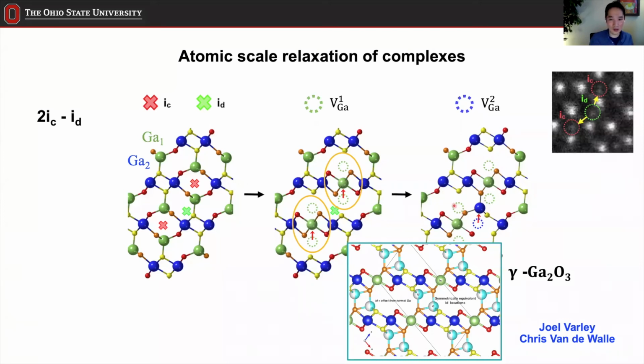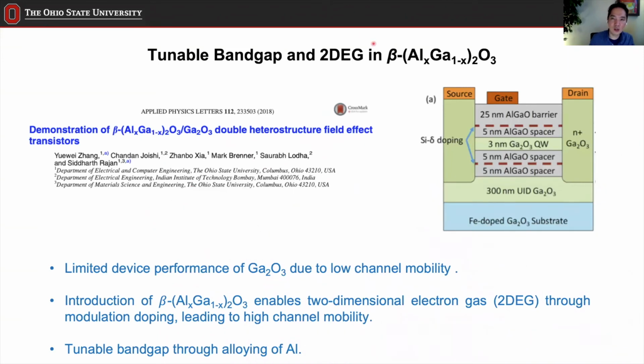Now, we're not trying to say that this is a phase transformation, one, because the structure doesn't match completely. And also, even if this is some kind of phase-transformation-driven event, it's very localized, and the lattice is not defined, so it's definitely not a complete phase transformation. But at least we have the signature of such evolution of the phase toward a structure that resembles the metastable gamma phase. That's what we found here. The gamma phase is something I'm going to explain in a few moments when I get to the aluminum gallium oxide too. So that's the end of the gallium oxide part that I wanted to show you today. For the last 10 minutes or so, I can go into a little bit of the aluminum gallium oxide story.